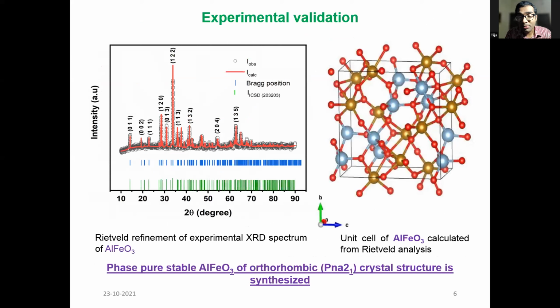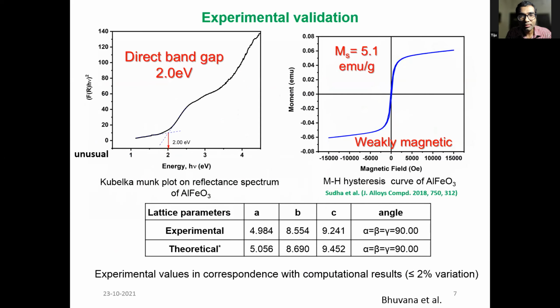So here is the experimental validation, for which I ought to thank Bhuvana, who worked for almost a couple of years to get a stable phase and this particular phase and so on. So you can see that we now make aluminum ferrite in our lab, and in fact, a wide range of such compositions exist, but this is a representation of what we have gotten, and you will find that it is a perfectly single phase. Next slide, please.